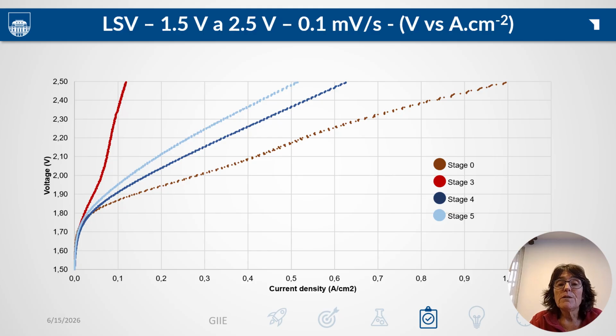And after stage 5, the post-regeneration potentiostatic degradation step, the curve only slightly degrades from the regenerated condition. The fact that some performance is not recovered tells us there is also an irreversible component of degradation, which we will see more clearly in the impedance data.